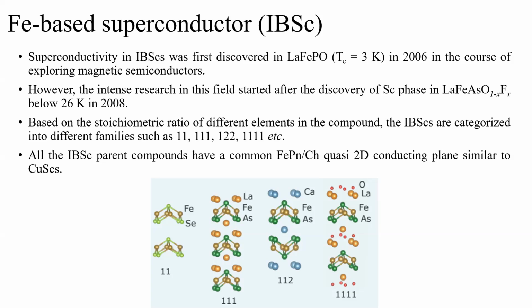In the case of cuprate superconductors, it was the copper and oxygen layer. Then one interesting point that I should make here: in copper-based superconductors, these copper and oxygen layers were almost two-dimensional. If you reduce the two-dimensionality and make it almost three-dimensional, the superconducting phase becomes a little bit difficult to find. But in this case, the superconducting phase appears only if the iron-arsenic or iron-pnictide bond lengths are around 2.4 angstrom, and there is a bond angle also. So the bond angle never goes to 180 degrees.